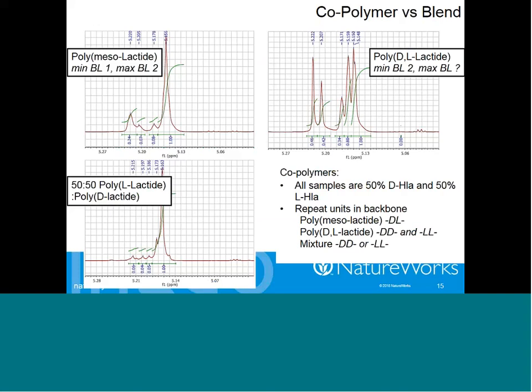Now the next slide shows the decoupled NMR spectra of the methine region, so the CH region, of a polylactide. I've spent a fair amount of time pointing out that we make a copolymer of D-lactide, mesolactide, and L-lactide, and sometimes the D-lactic acid content can be an instructive or useful analytical assessment of the polymer to help describe the properties that it will have.